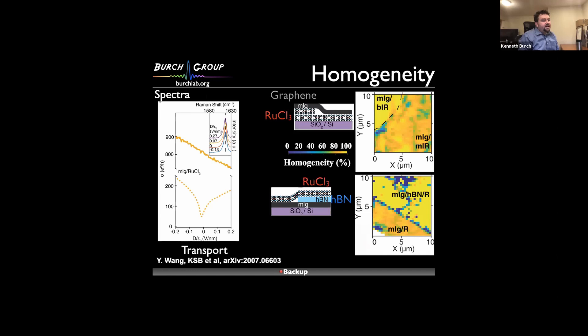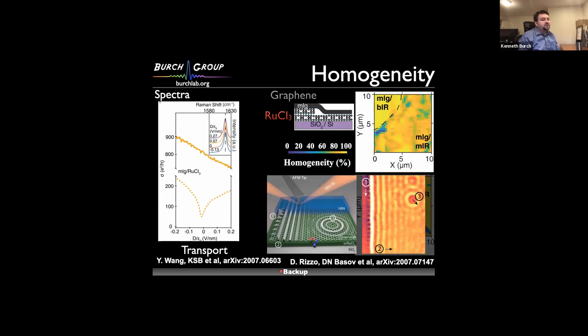What was very exciting was to see the results also from Dimitri Basov's group, where they made similar heterostructures and using near fields could see a variety of different kind of plasmon resonances, including edge plasmons, due to this very sharp interfaces that you get and bulk plasmons. From their bulk plasmons, they get doping levels consistent with what we see. That's this number two in the image on the right. However, you see this number three, which is a sort of a defect that they find. What they found was that they could explain that due to a very small, sort of a few nanometer size region which is totally undoped, which is consistent with what we find for the homogeneity response in the Raman.